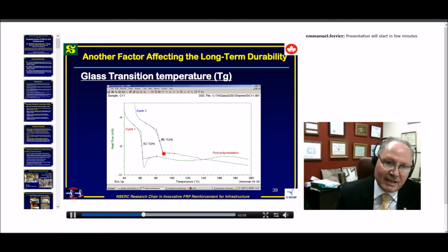But when we did the cycle 2, as you can see here, it's a continuous straight line. So the system was now fully cured, and as you can see, we jumped the Tg from 62 to 85 because we did some post polymerization, and it showed that the resin is cross-linked.